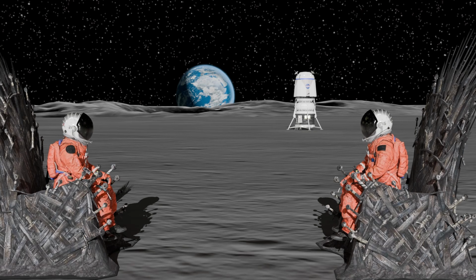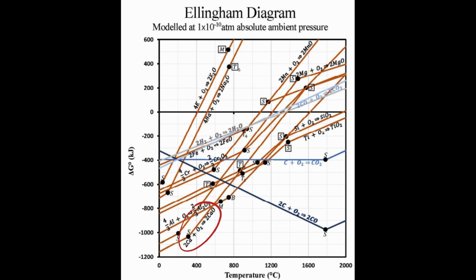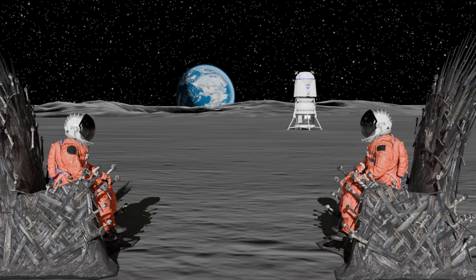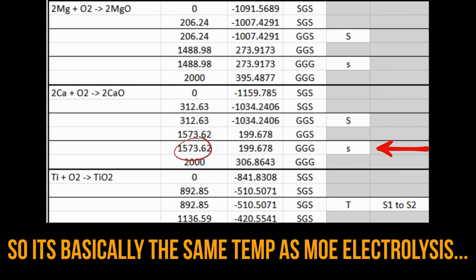But once you already have that calcium oxide in your process, then you can use pyrolysis. I would imagine in the initial sense for production, you would do some electrolysis just for calcium. You could avoid the electrolysis process and go straight to pyrolysis, but you're going to have some difficulty with the calcium efficiency-wise. You're going to have to reach some pretty high temperatures. Well, according to 10 to the -10 atmospheres, calcium oxide thermally decomposes and sublimates at about 1550 degrees Celsius, if I remember, while molten oxide electrolysis is done at 1600 degrees. So it's like a 50-degree difference.